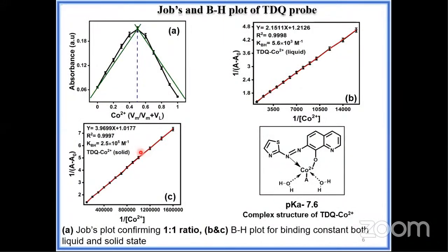We have prepared the TDQ probe ligand, formed by reacting 2-aminothiazole with 8-hydroxyquinoline. We also confirmed the complexing ability of the ligand using Job's plot and BH plot. In Job's plot, it confirms that it forms a 1:1 ratio complex, and in the BH plot, we get the binding constant. In liquid state, it shows 5.6 × 10^3 molar inverse. Also in solid state, it shows 2.5 × 10^5 molar inverse. These are the best indication that the probe has a stronger affinity in the solid state medium.